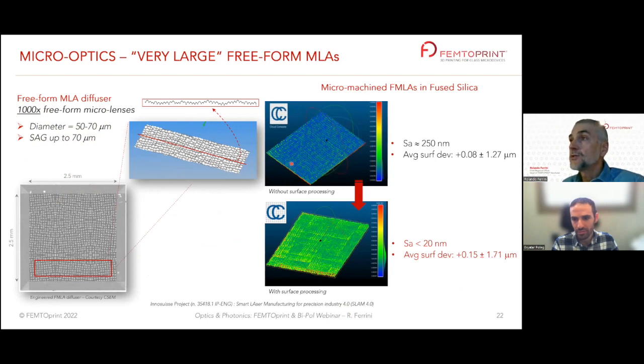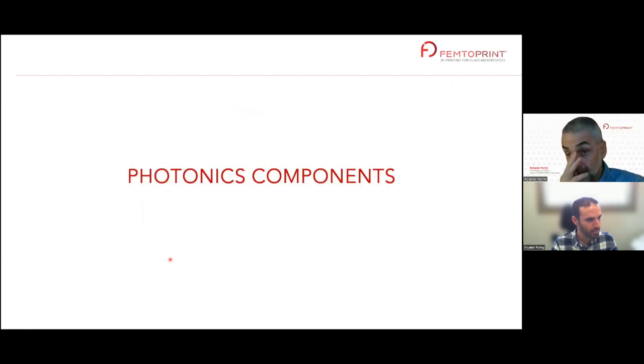Here you see the result after the first part of the process. Average surface roughness 250 nanometers, can be improved down to 20 nanometers or better, losing a bit in shape accuracy. This was not really a problem for this application. Actually, this was used for lighting application, for beam shaping for lighting, and was enough. So it depends also a lot on the type of application you're looking for. So that's the status for miniaturized and micro optics.